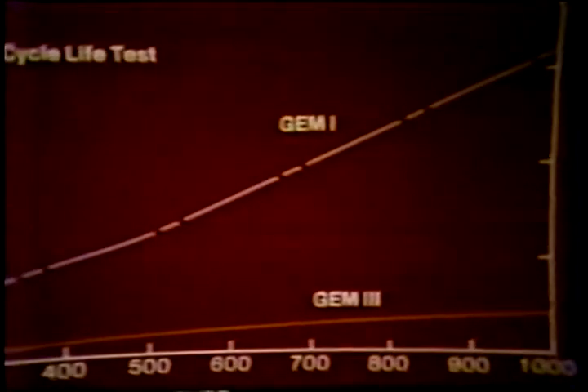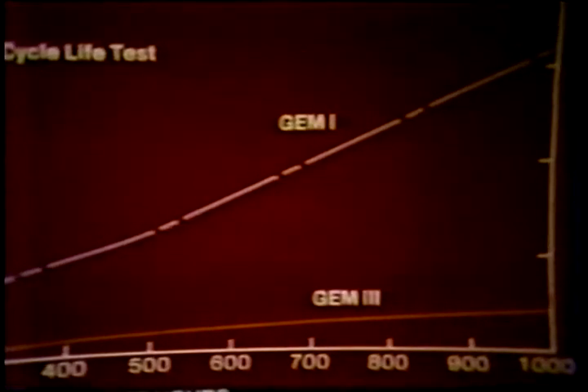The capacitance loss is plotted here as a function of time that these capacitors were on life test. The Gem 1 designation indicates the standard processing and standard aluminum electrodes. It shows a much higher capacitance loss than those present with the Gem 3 capacitors, which have the improved processing and non-corrodable electrodes.